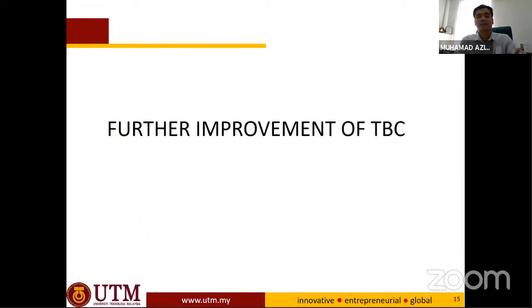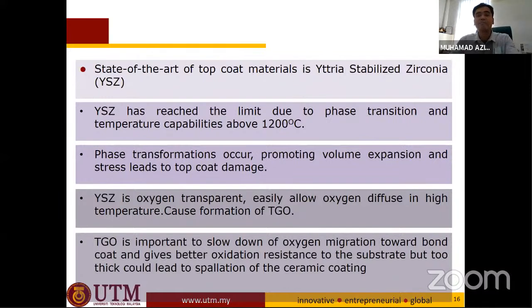Okay. So we have the normal TBC, made of yttria stabilized zirconia. Because of the evolution of gas turbine engines, there is a need for improvements of the ceramic coating. We know that YSZ, yttria stabilized zirconia, is very good, but it reaches a limit. The limit is up to 1200 degrees C, which is why I showed in the figure earlier that the maximum temperature is around 1200 degrees C. Above this, there is a transformation from tetragonal to monoclinic.